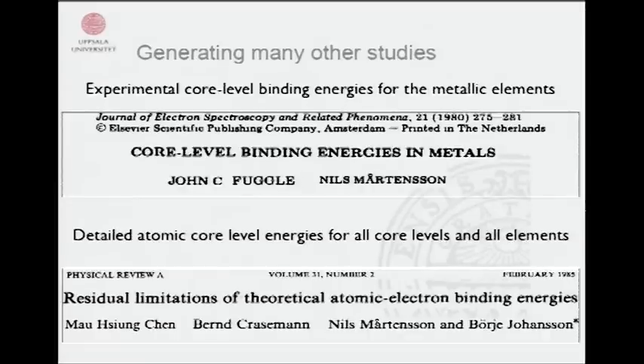And we compared that to atomic theory, looking at, of course, correlation effects, but also relativistic effects and these things. One thing that started out as a sort of failure: we couldn't get this nickel satellite, which was very much discussed in connection with correlated systems, in the right position. But after a while, we got it when we realized how these multiplet effects played a role here. So we had one paper in PRL about that.